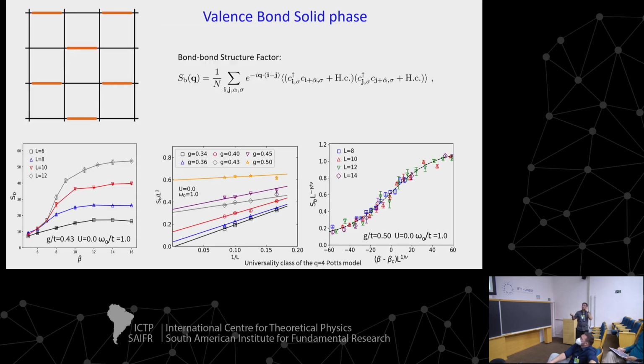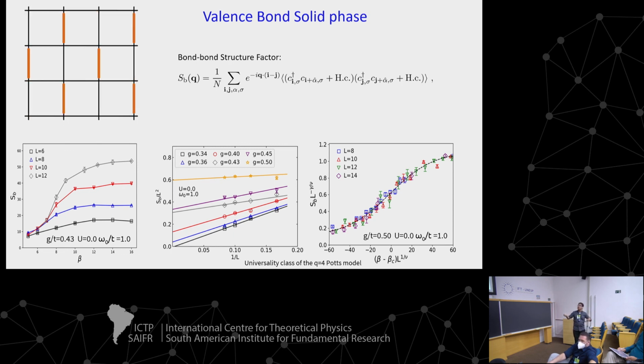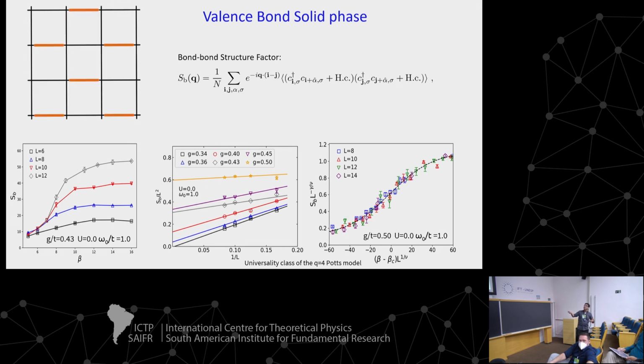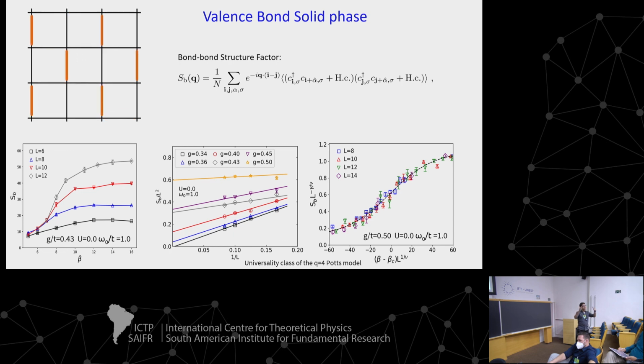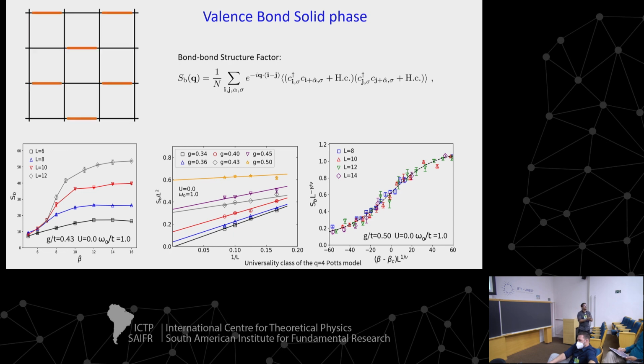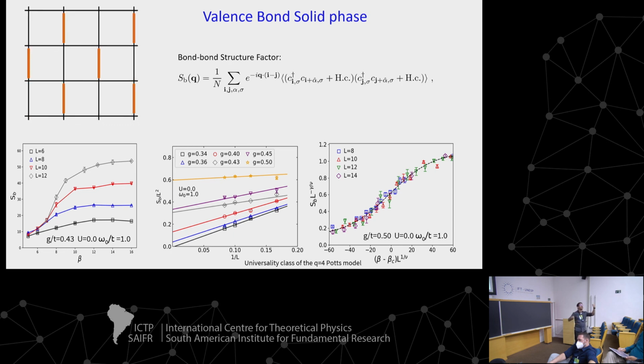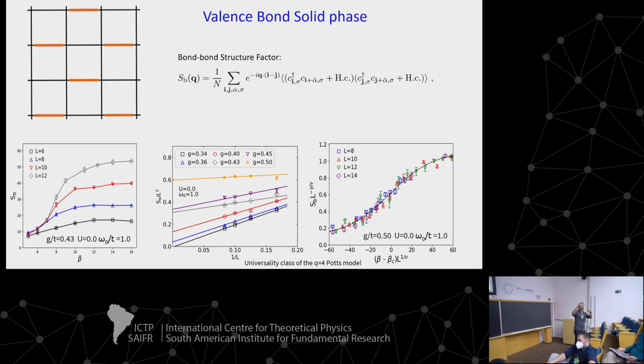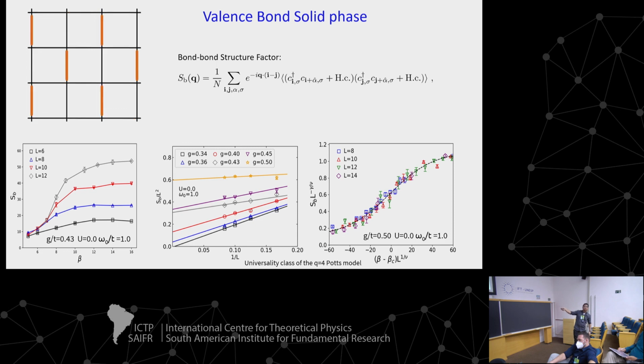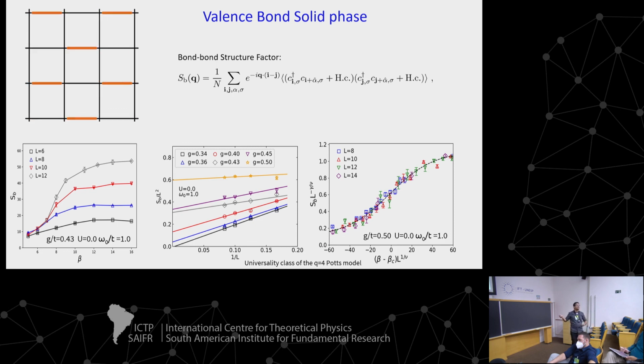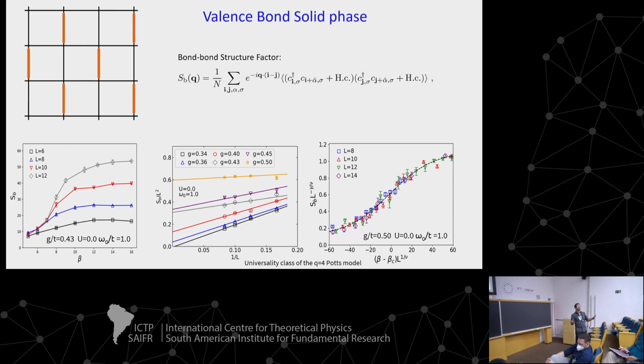This is our result. What we did was we analyzed the bond-bond structure factor for different lattice sizes, and then we performed some kind of data collapse to investigate where the critical point is, because if we are at the critical point, all of the data from the order parameter should collapse onto the same curve. So this is what we did here. And the critical exponents we already know, because this is in the Q=4 Potts-like universality class. We can discuss it later.